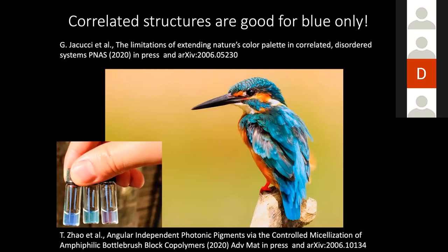This angular independent color is interesting, but it is mainly used in nature to produce blue color. So this was another cool finding that we recently got published in PNAS: if you look at color produced by this correlated structure in nature, you only find blue and UV hues, but you never observe red. And this was really cool for us to see, because if you try to artificially reproduce this type of structure and scale it in order to achieve different hues like green and red, the red color that you obtain exploiting this natural design is never really great.